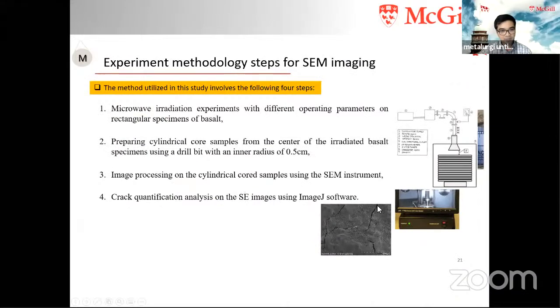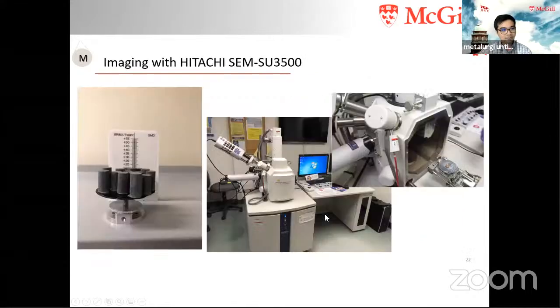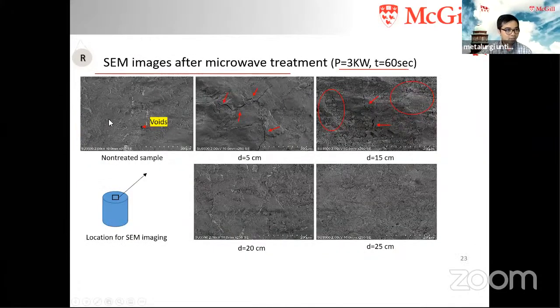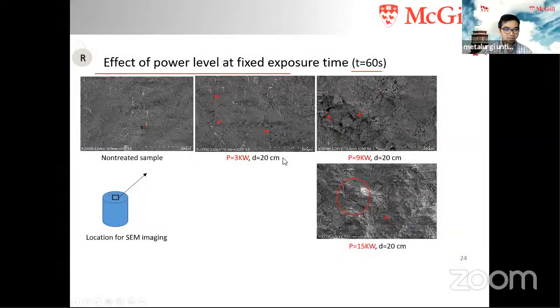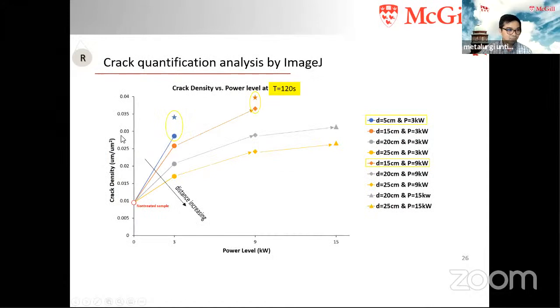And we can see here after the rock is microwaved, it creates micro cracks. We also quantified using the non-treated sample. Basically, there is almost no micro cracks in it. When we microwave the sample at 3 kilowatt and 60 seconds with different distances from the microwave antenna, we get different crack patterns. This is another example of the result. The result is summarized here: when we increase the power level of microwave, the crack density increases. And when we increase the microwave duration, it also affects the crack development.